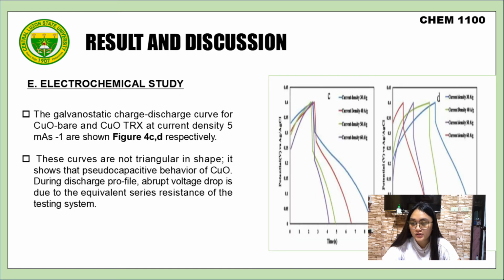The galvanostatic charge discharge curves for copper oxide bare and copper oxide TRX at a current density of 5 mA/s are shown in figure 4C and D respectively. These curves are not triangular in shape. It shows the pseudocapacitive behavior of copper oxide. During the discharge profile, an abrupt voltage drop is due to the equivalent series resistance of the testing system. Next slide, please.